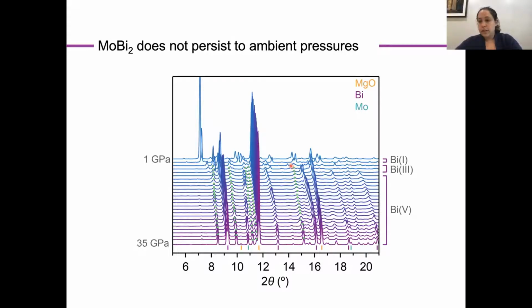And in some ways, this is a challenge because it means we can't study these materials, can't hold these materials in our hand and study them at ambient pressure. But it's also not surprising because this is exactly the same behavior that we observed in the manganese and iron analogs. And so once again, I was wondering what type of insight we could gain from the fact that we now see this behavior so commonly.